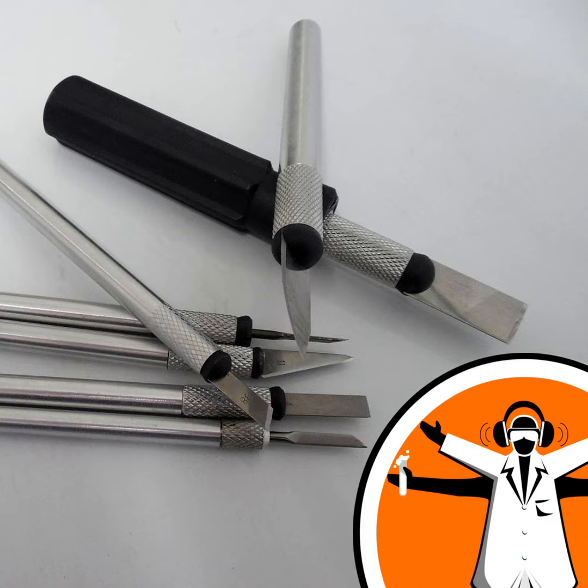Have they tried this in real applications? They have. They applied this coating to a surgeon's scalpel. What they found was the amount of E. coli that stuck to the surface of this treated steel was reduced. What they also found was that if they used a scalpel covered with this coating, it gave a much cleaner cut. Ben DeLorme from the University of Birmingham, commenting on research carried out by Harvard University researchers, published this week in Nature Communications.